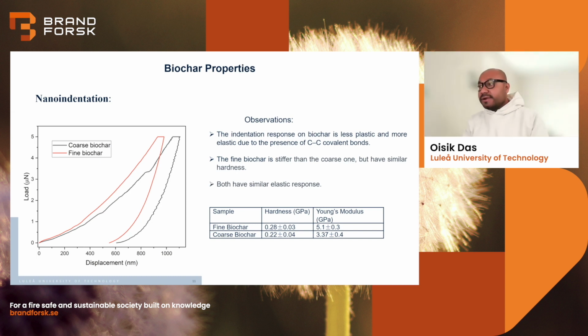So what we have seen here is that both biochars are more elastic in nature, which means that once you press down with the known load using an indenter, which looks like a pin, but the tip, its technical term is Berkovich, what happens is that once you load the pin and then you unload, the impression area kind of disappears because it's elastic, but not fully disappears. This is called elastic response, and this is because biochar has carbon-carbon covalent bonds, which are quite strong.